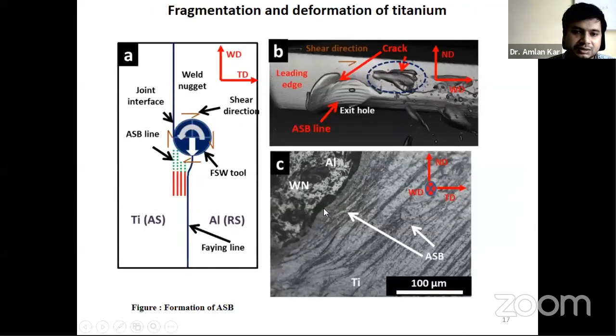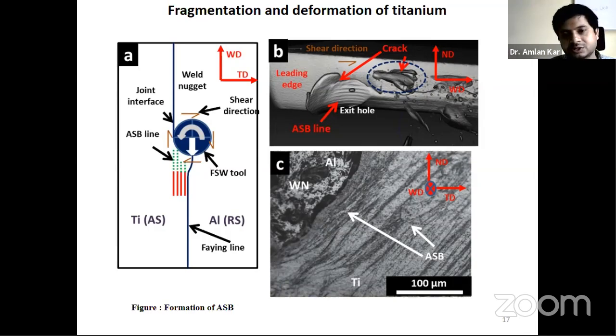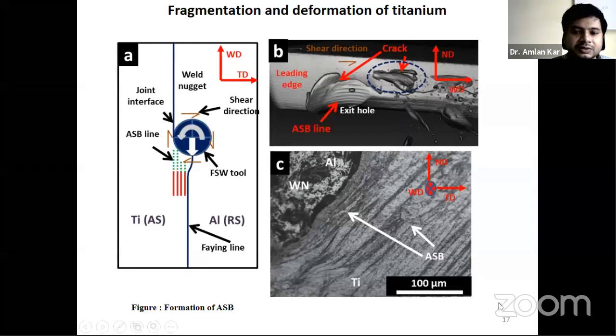And there are a few examples from the microstructural point of view. You can see from the optical microstructure that there are adiabatic shear band formations, and these adiabatic shear bands are parallel to each other, acting along the shear directions. Because at the advancing side, the flow of the material is from the bottom to the top because of the hydrostatic pressures and because of the shear rotations as well. So we can see there is a deformation direction. We can see there is a mark of the adiabatic shear band line.